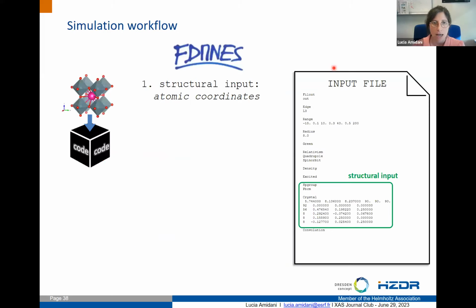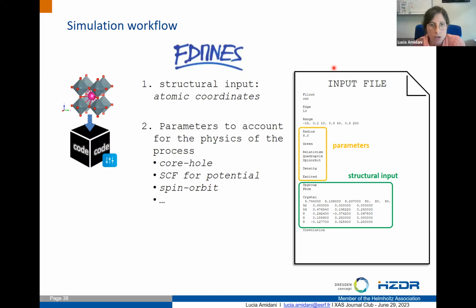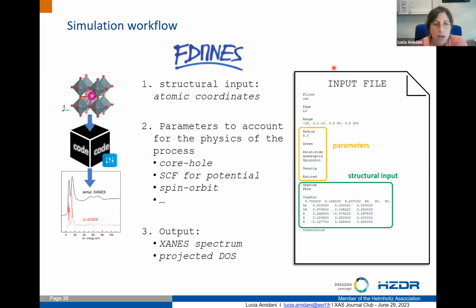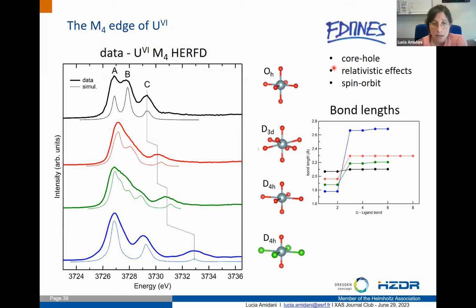Again, my approach was to use XANES, whose main input is the atomic coordinates of our structure. We have some parameters to tune the physics we are taking into account, and as output we get the XANES spectrum, but also the projected density of states. This is the best agreement we get, which I find pretty nice, because despite each simulation not being perfect with the data, the trends we observe in the series are reproduced.